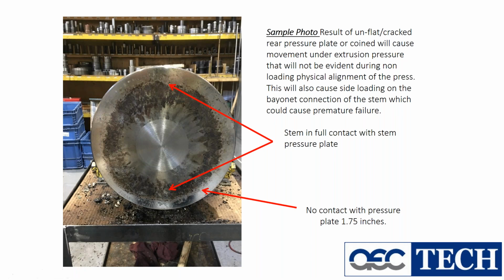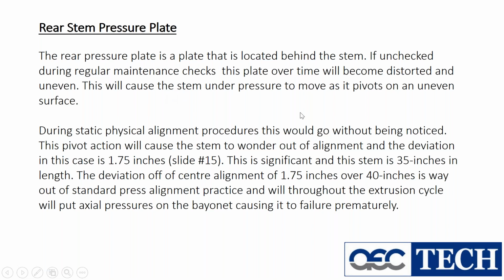Once we pulled the pressure plate, we found the pressure plate was coined. The problem with that is, if the rear pressure plate that's located in the back of the stem, if unchecked, it can, during regular maintenance, over time the plate will get distorted. Under pressure, even if the press is aligned, the stem under load will move. So if we take a look at that stem that was offset or pivoting on 1 3/4 inches, like back in slide 15, if that stem slides over 40 inches,